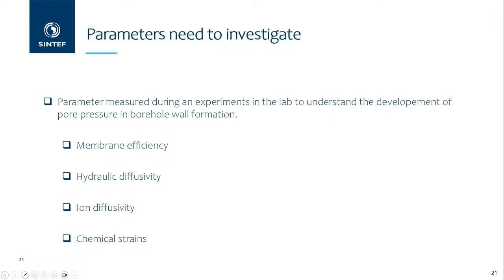So now you understand why the pressure moves, why the fluid is moving, so ions going in. But since you have clay minerals, and I'm talking about an abundant amount of smectite in your clay, what happens if you have some sort of ion, mainly potassium, that moves into the shale and kicks the sodium ion out of the shale? The lattice becomes smaller and the sample shrinks, and that is chemical strain. And if you just have water, no ion, fluid will go in, and the lattice in the smectite will expand. Yeah? So this is chemical strain, which is very important.